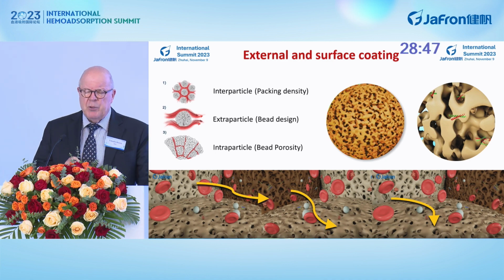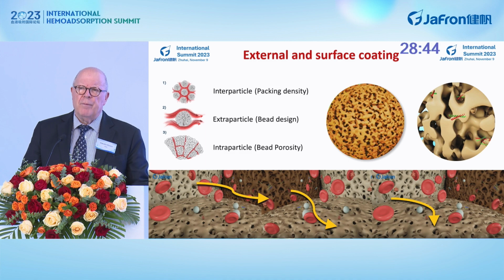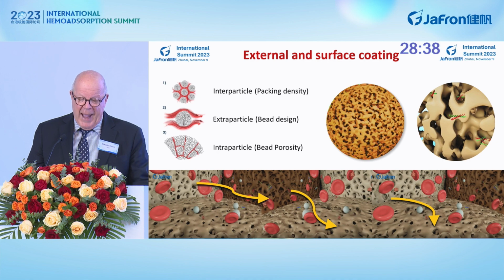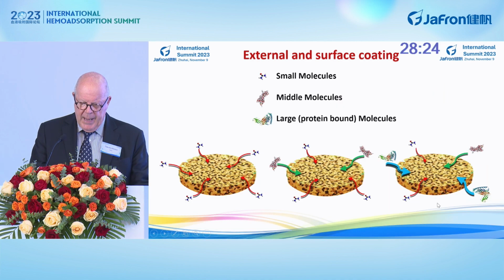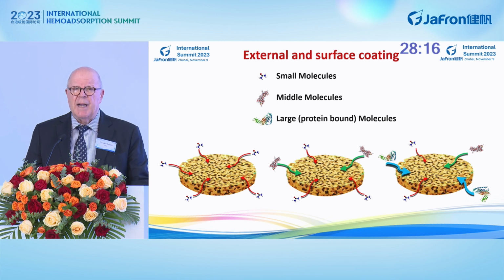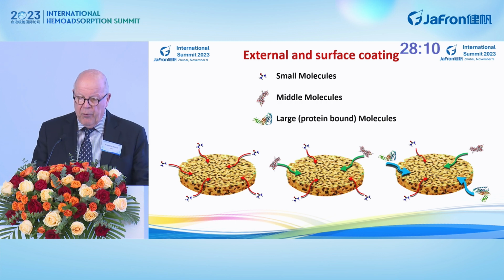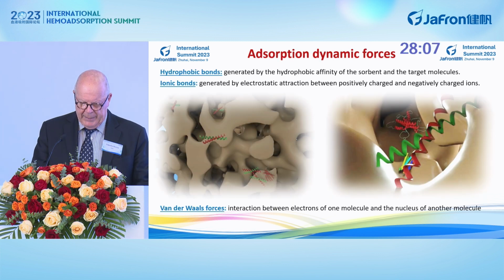So we have to consider the different flow of the fluid phase through the sorbent in terms of interparticle flow, extraparticle flow, and also intraparticle flow with internal convection. And you see that the flow of the fluid phase sometimes has to go through the bead inside. At this point, coating must not prevent the diffusion of different molecules from outside to inside the bead. And in this case, as you can see here, porosity and coating must be combined.